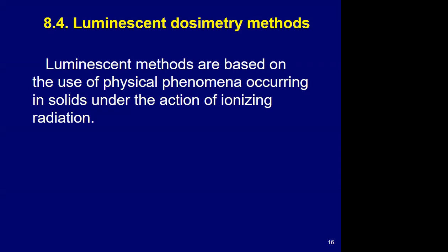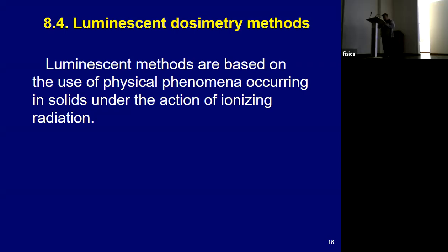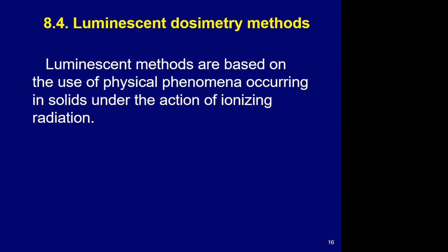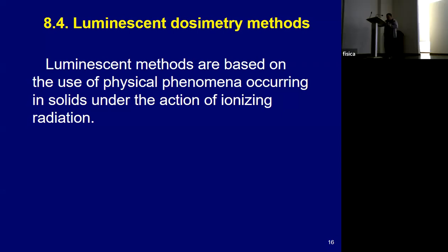Single crystal of lithium fluoride activated by magnesium and titanium. Lithium fluoride single crystal activated with magnesium, phosphorus, and copper. Also, aluminum phosphate glasses activated with magnesium. Single crystal corundum, or aluminum 2 oxygen 3. And magnesium borate polycrystal activated with dysprosium. Alkali compounds such as sodium chloride or lithium chloride, and metaphosphate glasses activated with silver are used as photoluminescence detectors.